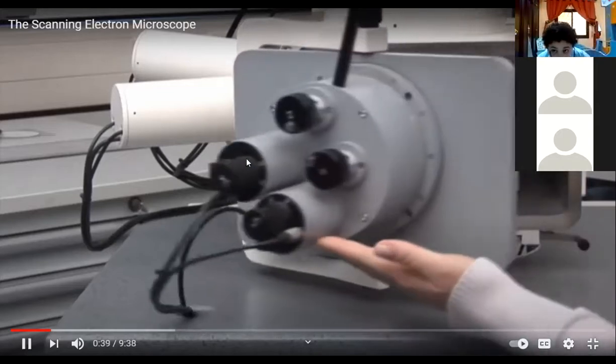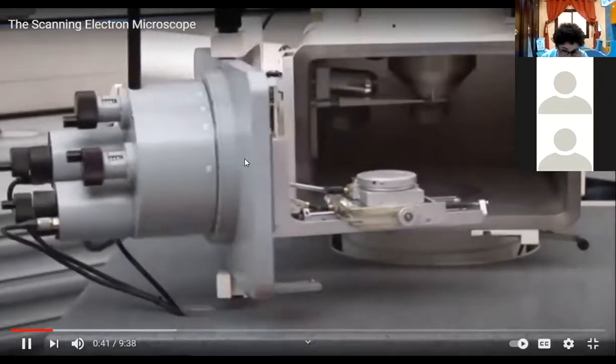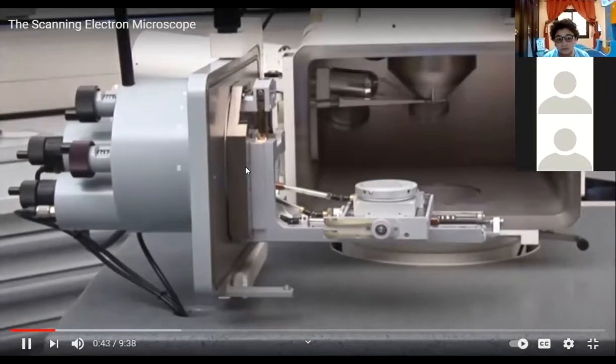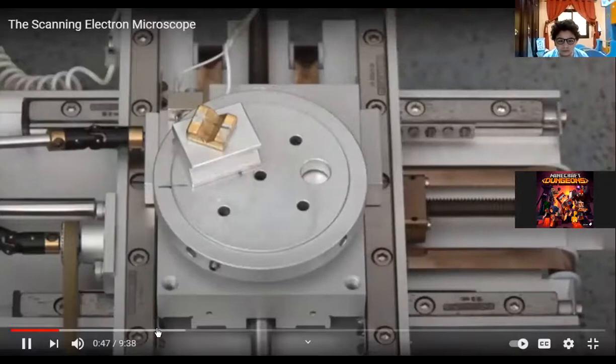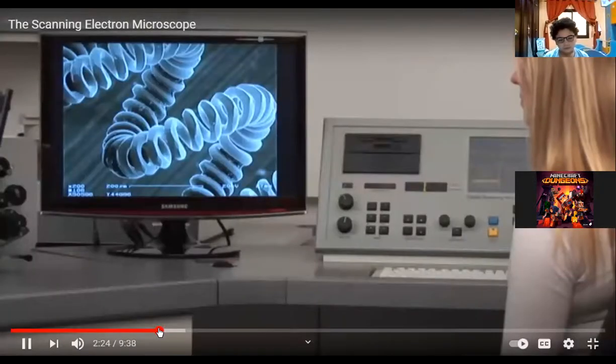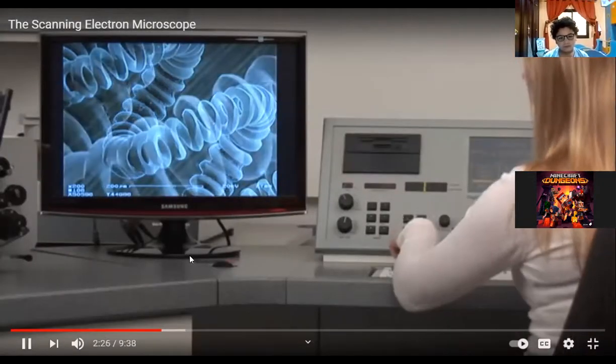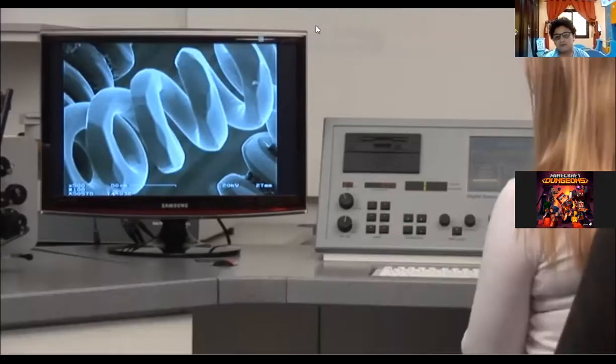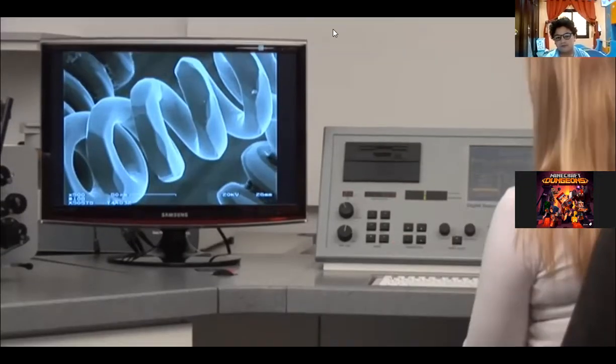The stage pans forward. Now different specimens can easily be placed on the round stage. The filament of an old used light bulb is on the monitor. Originally, the coiled coil filament was quite smooth on the surface. Caused by the everyday use of the filament, new crystals have been formed. Tungsten atoms have evaporated and the outer regions of the filament have become polygonal.